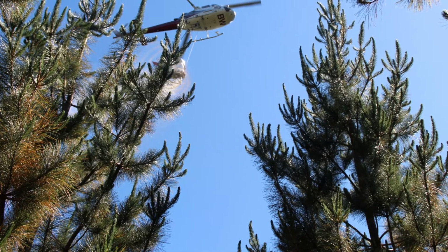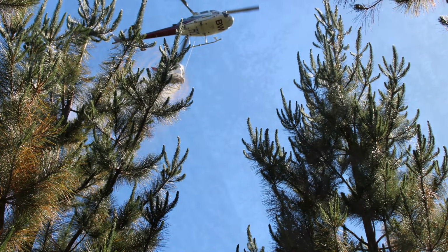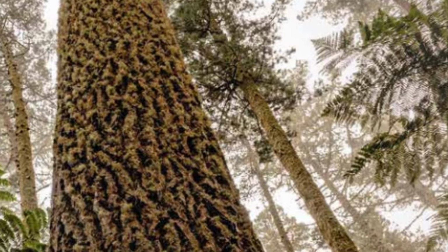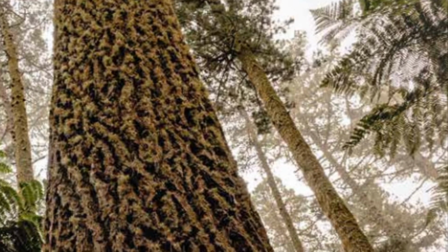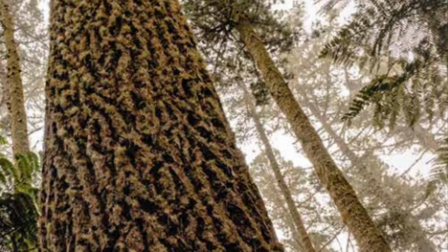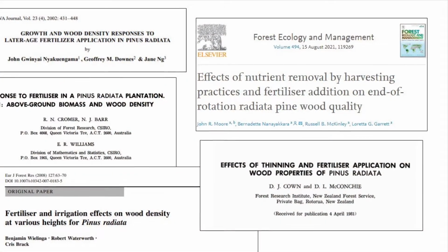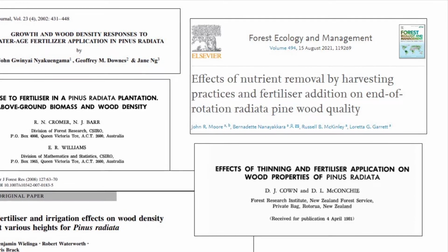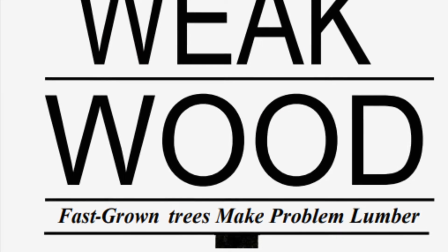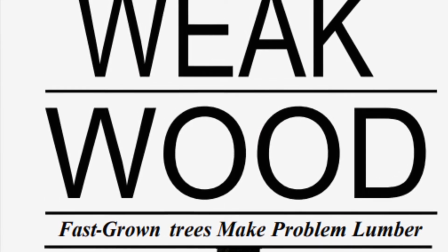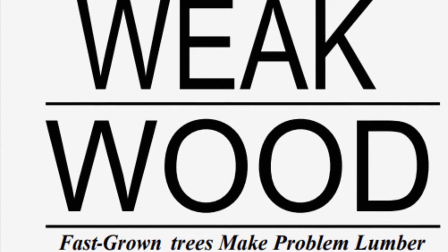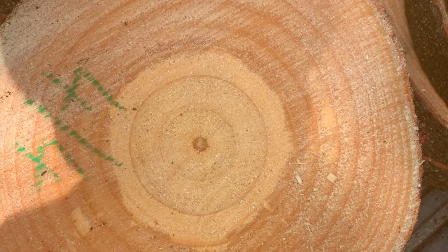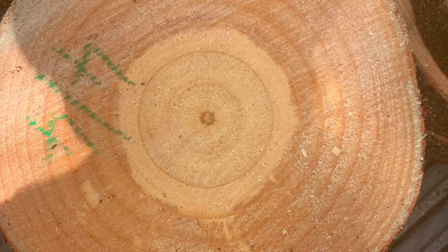There have been concerns around the impacts of productivity enhancement on wood quality. Take genetics, for example. We know that traits such as density and stiffness have adverse genetic correlations with growth traits, and this was particularly apparent in clone 55. Nutrition is another area where there was the perception that applying fertiliser would lead to a reduction in wood density. Finally, if we do manage to increase productivity, it follows that rotation age will reduce, and here again there have been concerns expressed that wood quality will suffer. Therefore, it is important for us at Timberlands to understand the impacts of our productivity enhancement strategy on wood quality.